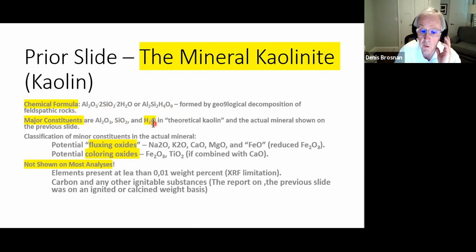The OHs, the oxygen and hydrogen, are combined in kaolin as hydroxyls in the crystal structure. And of course, when kaolin's heated, those hydroxyls are going to come zinging off. They don't like being by themselves in the atmosphere, so they combine with hydrogen immediately and form water vapor coming off. Now we can classify those constituents as major constituents, alumina and silica.